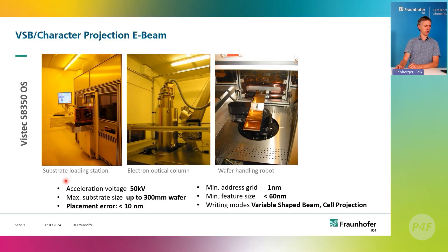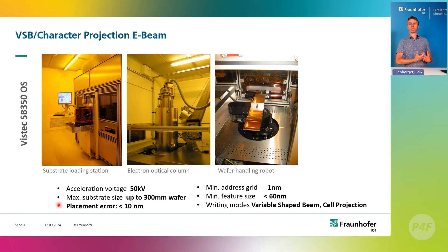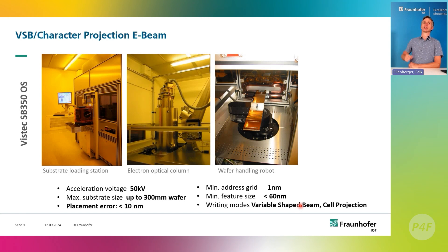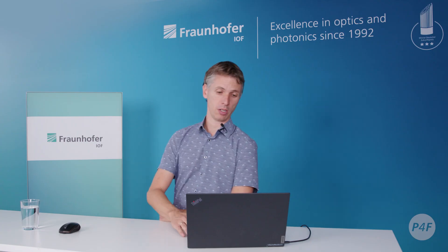The minimum feature size is not exceptional by electron beam lithography standards, but that rarely matters for metasurfaces. Where this machine really excels is in accuracy: placement errors are very small, so an antenna placed at a given point on the wafer is really there to plus or minus 10 nanometers. It's also a very fast machine, thanks to the writing modes I'll discuss next — which matters for cost, since we really want to create elements we can ship to customers.